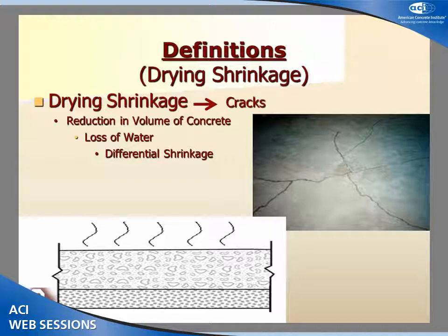So what is drying shrinkage? Drying shrinkage is defined as reduction in volume of the concrete due to loss of water. How does this process happen? When the concrete dries, the free water of the concrete evaporates from the top surface of the concrete. So the top surface of concrete shrinks, while the bottom surface and core of the slab don't tend to shrink as much as the top surface. So a differential shrinkage develops through the depth of the slabs.